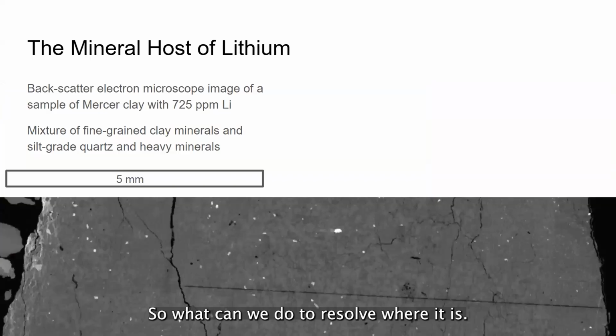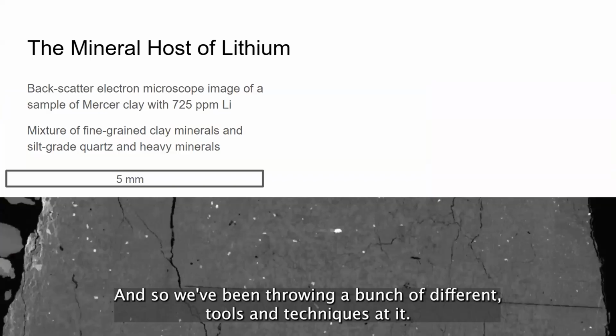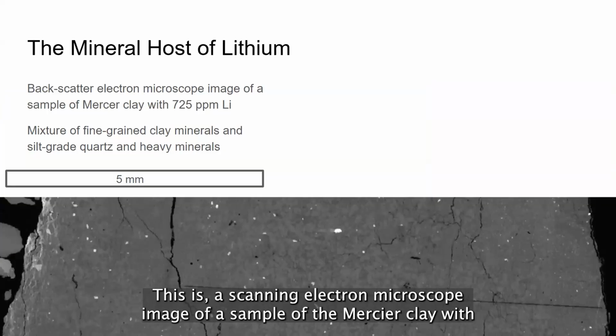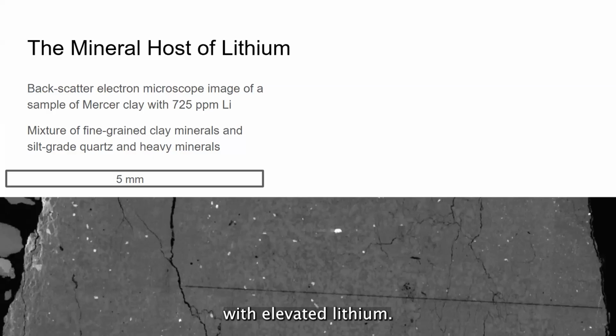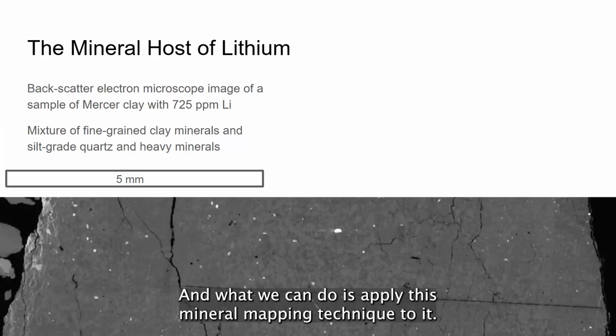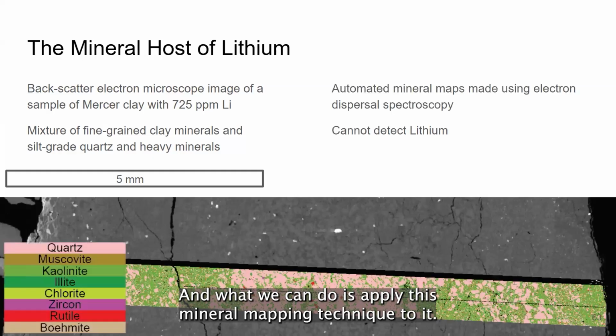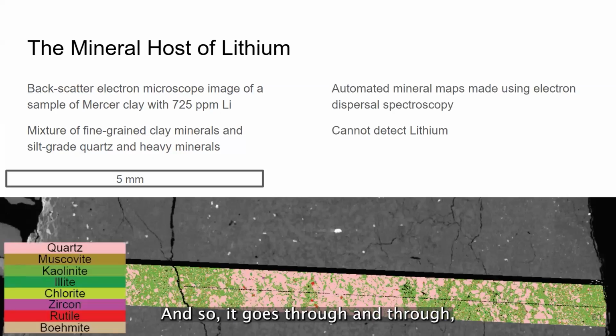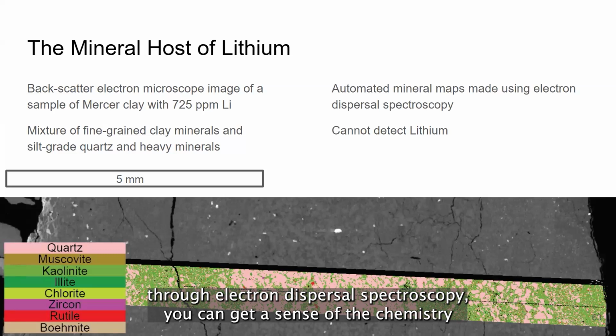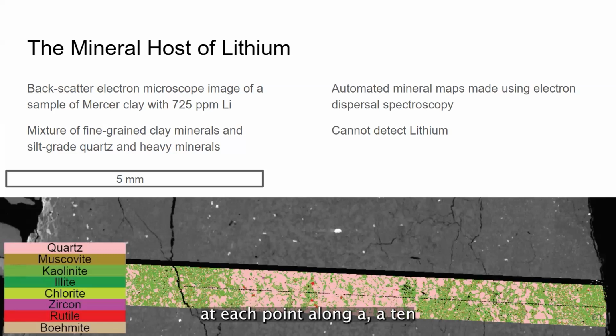So what can we do to resolve where it is? We've been throwing a bunch of different tools and techniques at it. This is a scanning electron microscope image of a sample of the Mercer clay with elevated lithium. What we can do is apply a mineral mapping technique to it. Through energy dispersive spectroscopy, you can get a sense of the chemistry at each point along a 10 by 10 micron pixel size on this sample.